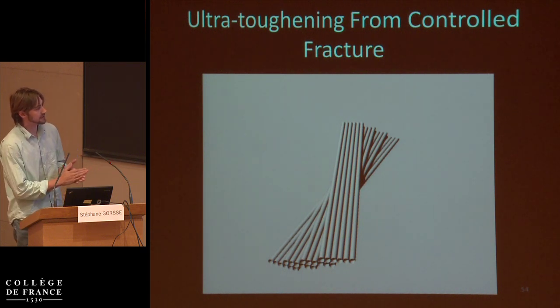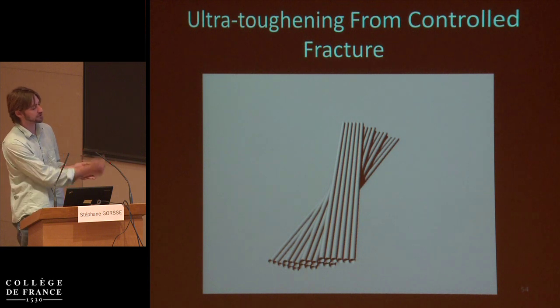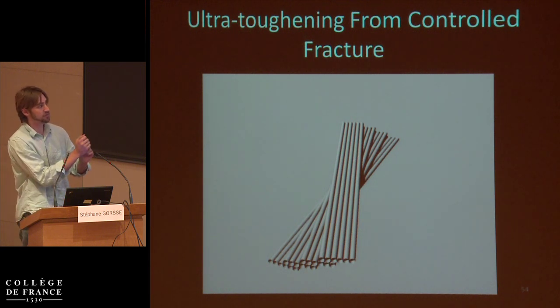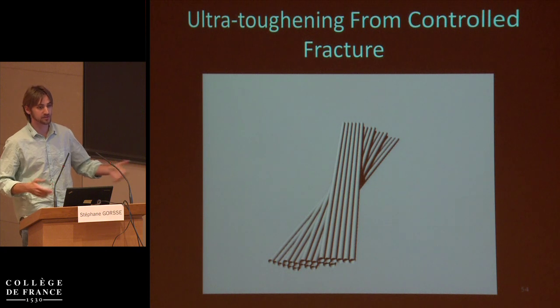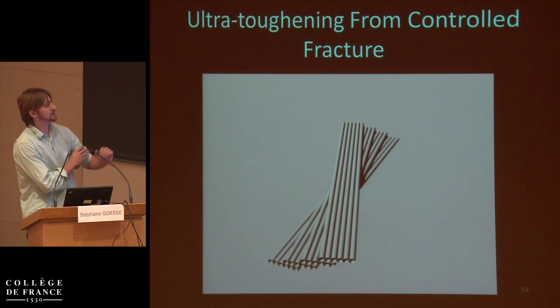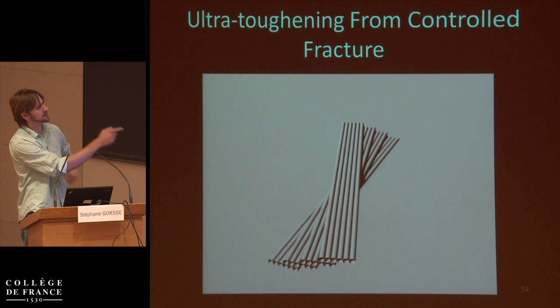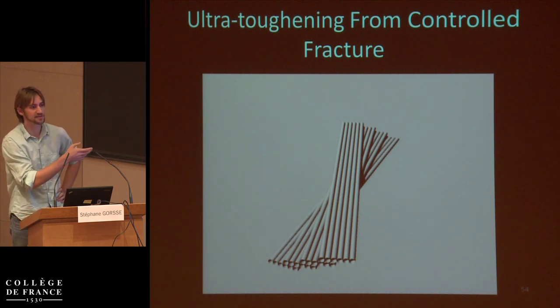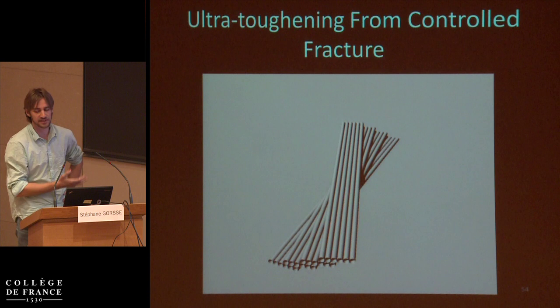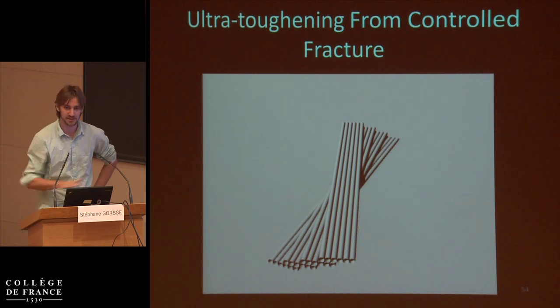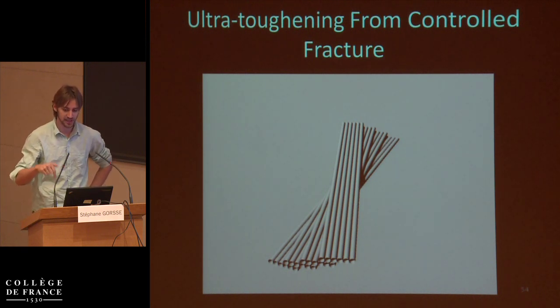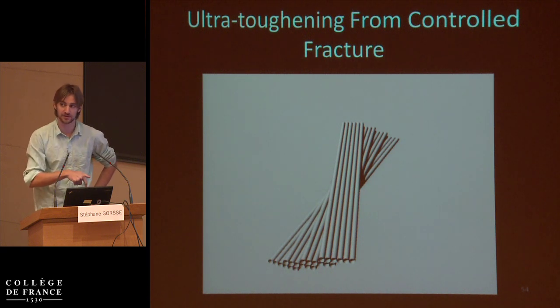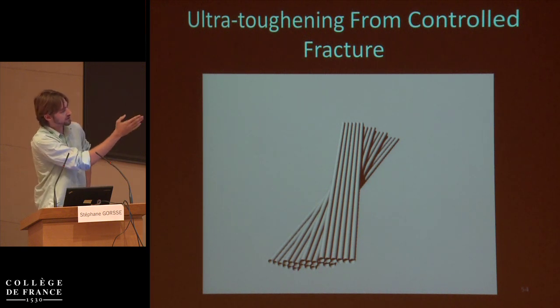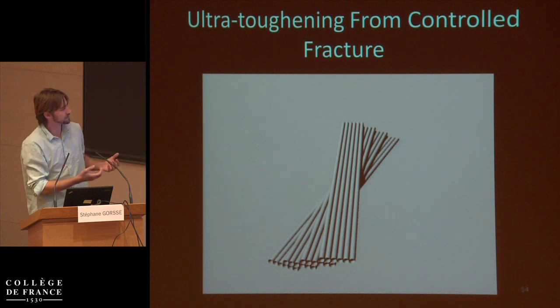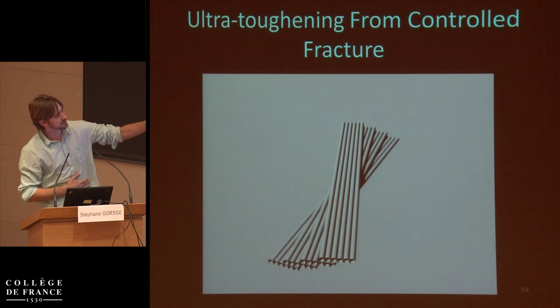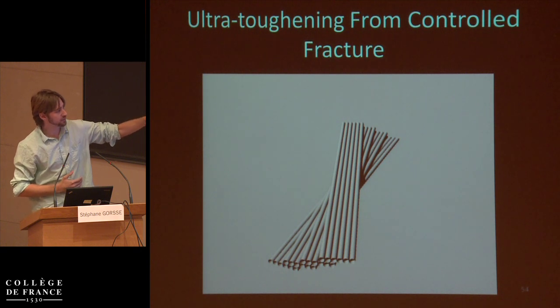So if we then consider and increase this depth a bit, then you could see another mechanism, which is that if we consider growth in the vertical direction that's from something that's already grown radially, which is the last regime we would have to consider, you can see that there's something interesting about a helicoidal composite that maybe isn't completely obvious, and that's that there really is no central axis. So it's a translationally symmetric composite, so you can choose anywhere you want, and that's an axis for a helicoid. So because fractures are a local phenomena, there's no reason for a fracture to actually stick to one specific helicoid.